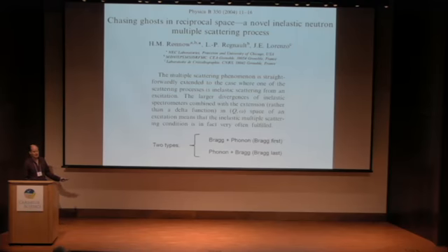In fact, there are two types that this paper considers. One where you have parasitic Bragg scattering first and then followed by a phonon. So that parasitic Bragg scattering acts like a second monochromated incident beam that's tied to your crystal. And the other one is where you have phonon scattering first that then satisfies the Bragg condition, and you get, again, a double scattering peak. Okay, we're going to consider the first case.